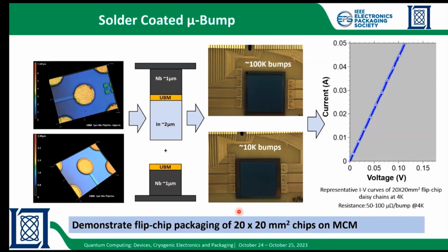And also the bump bonding yield is going to be very high. Here we have yielded up to 100K bumps. So this approach produces high bump bond yield as well as low interconnect resistance. We're getting interconnect resistance at 4K for this kind of structure of about 50 to 100 micro-ohms, which is around 2.5 to 5x smaller than traditional indium bump interconnect resistance at 4K.